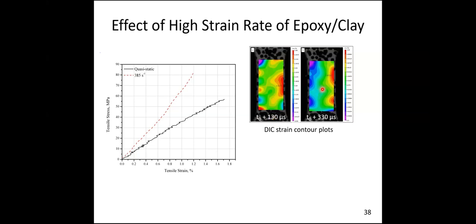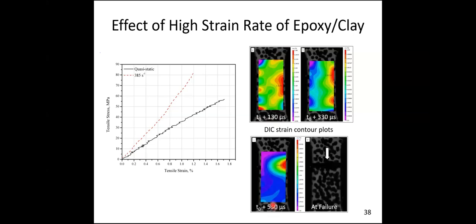When I keep on applying load, you can see there is a strain localization. Again at 330 microseconds, you can see a good amount of strain localization. Again at 530 microseconds, you can see a large strain localization or strain concentration. So this is the point where the failure is about to happen. This is the image taken just before the failure, and then we have a failure.